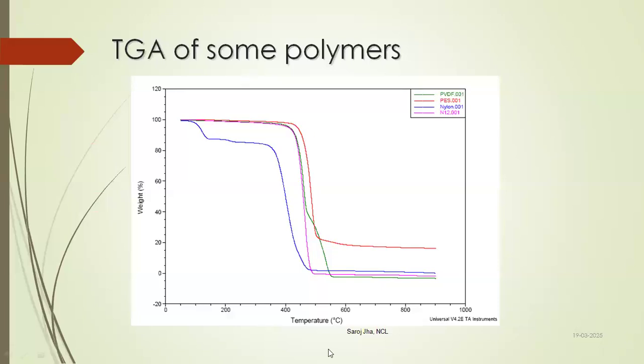So here, this is how a typical TGA curve looks. Y-axis is the weight and x-axis is the temperature. Now concentrate on the pink curve. As you heat the pink curve material, there is absolutely no change up to, let's say, 420, 430 degrees centigrade. And then there is a sudden weight change. And again, the sample stabilizes. So this is read as onset of degradation. This is the degradation pattern, and this is read as completion of degradation.